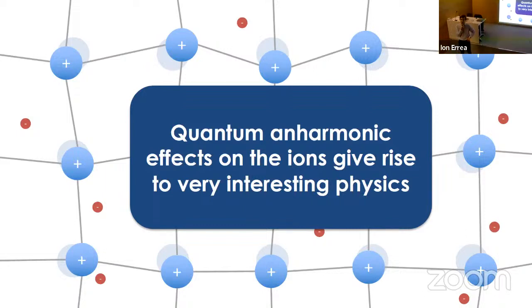First is HR. I have a very basic question, maybe even a bit stupid: how can you define a band structure starting from the Bloch theorem if you have anharmonic effects in the lattice? You're sort of assuming that the periodicity will not be perfect, right? No, I'm keeping the periodicity of the lattice perfect. The atoms move anharmonically, so at any instant of time the lattice will not be perfectly periodic. That's how I see it, or maybe there is a flaw in my argument. It is true, but let's say your average position has the lattice periodicity. So then you have the X-ray.